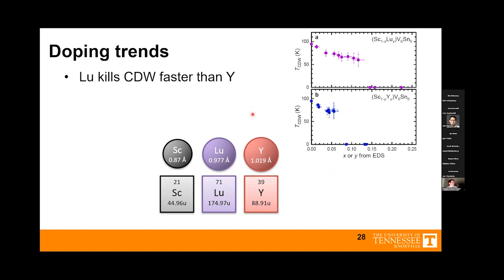Now, oh, I have written this wrong. Yttrium kills that charge density wave faster than lutetium. I'm sorry. You can see here that at this point our charge density wave is gone by 9%, where it lasts until at least 12% in the lutetium data set.